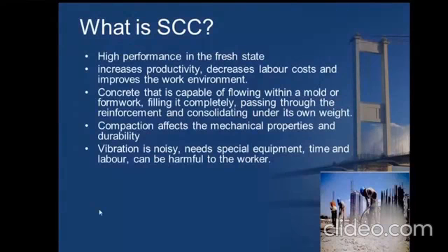You would be able to achieve a strength greater than 50 MPa, and you can even go up to 80 MPa. So it comes under the category of high strength and high performance concrete only. And as I told you, the advantages, the density and all those things are the same. Here you should make a note that the size of the coarse aggregate has to be limited, because as I told you, it is mainly used in situations where you have congested reinforcement. So generally we prefer to use 12 mm down aggregates. 12 mm down size aggregate is preferably used in self-compacting concrete.